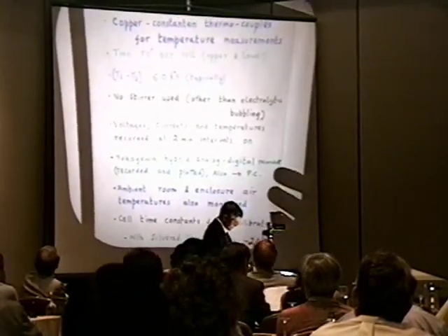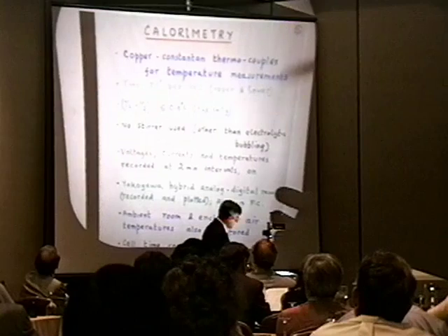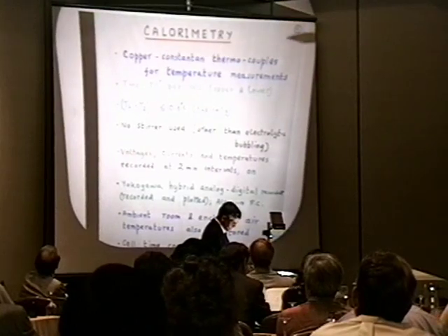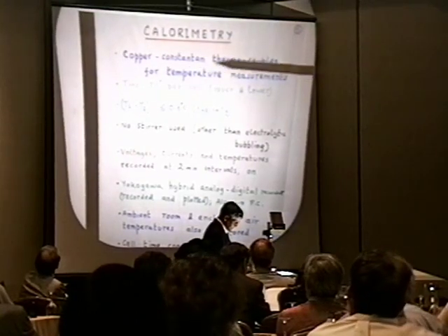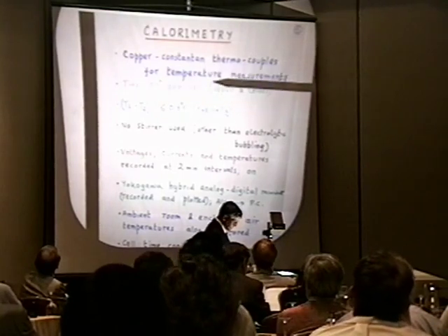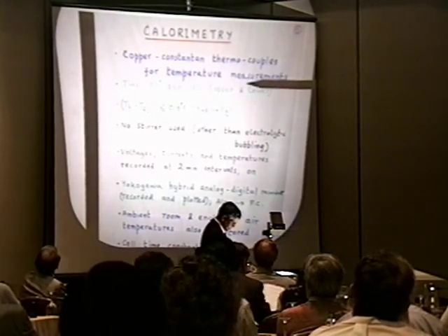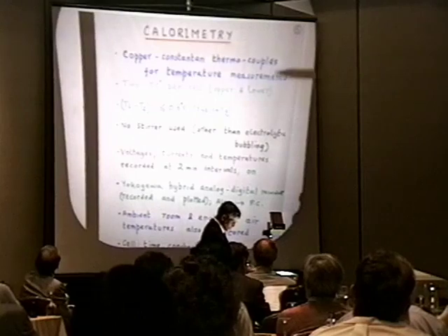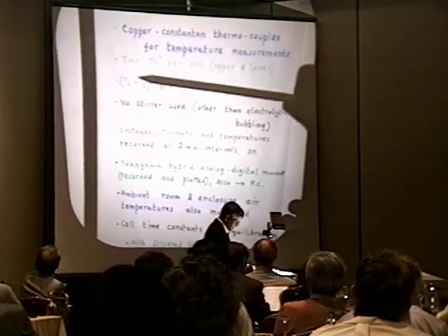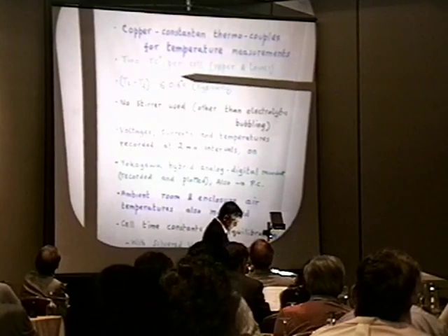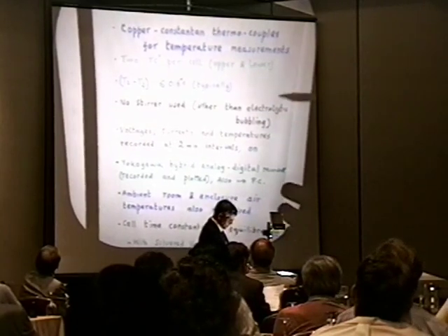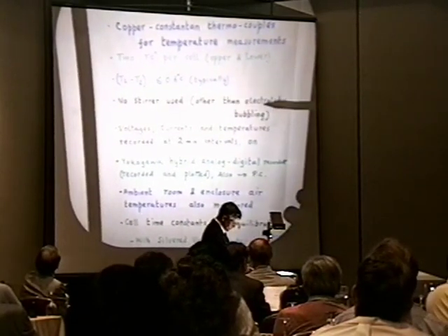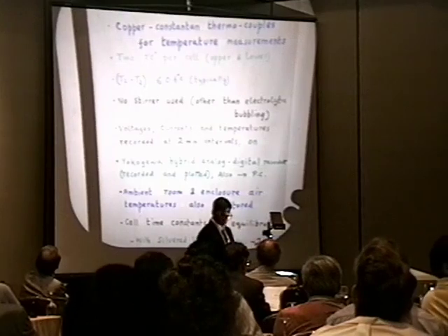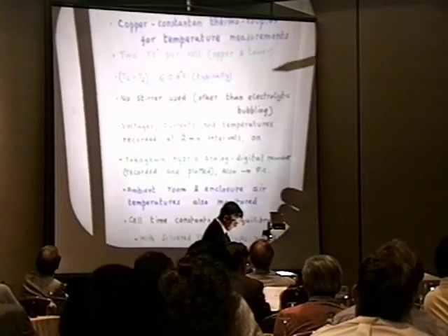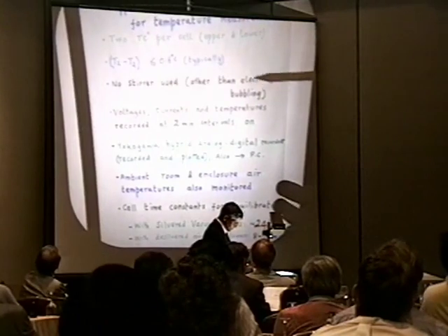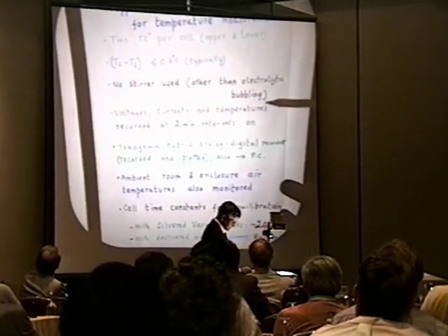The calorimetric technique is very simple. We use copper constantan thermocouples for temperature measurements. There were typically 2 thermocouples in each cell, one in the upper region of the flask, one in the lower region. Typically the difference between the 2 thermocouples was less than or equal to 0.6 degrees. No stirrer was used in any of these experiments. We had difficulty driving a stirrer through the commercial thermos flask. The only stirring was during the electrolysis due to the bubbles.